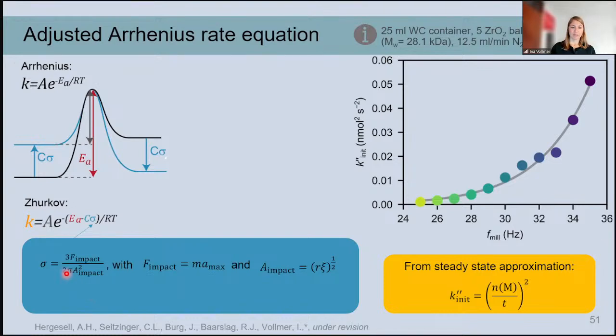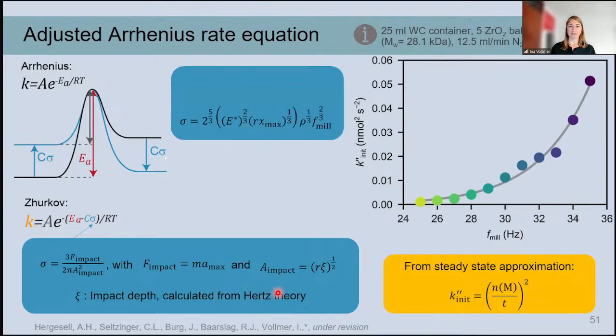And this we describe by the impact force, so the mass of the spheres times the acceleration, and the impact area. And to calculate the impact area is a little bit more tricky, because you need to know how deeply the sphere actually goes into the polymer material upon impact. And this we calculate from Hertz theory that I will not explain in too much detail here. But basically what this yields us is this stress, as a function of the stress, which is actually dependent on the milling frequencies to the power of 2/3.